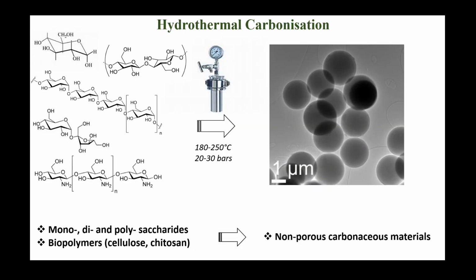But now coming back to these carbon materials, the way it works is that you need to have a lot of carbohydrates. Back in the time that I was a postdoc, and then because of this technique, I got an independent fellowship at the Max Planck Institute. I've been looking a lot at the fundamentals of this hydrothermal carbonization process, how these particles form, what is their chemical structure, and so on. Of course, this is an oversimplification, but in general, the nice thing is that you get monodispersed spherical particles from this hydrothermal carbonization.